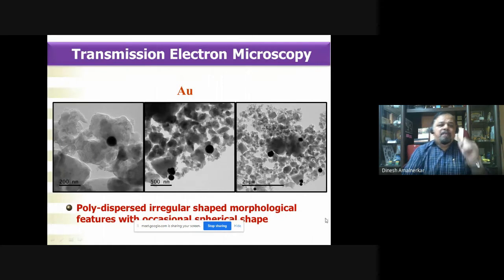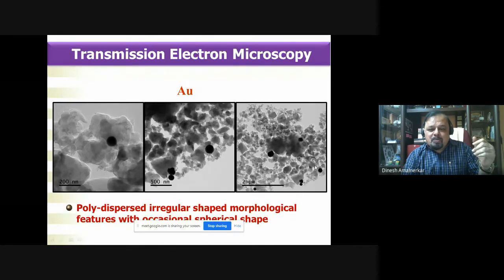Now, since we are not happy with the FESEM results, or so-called SEM results, we switched over to transmission electron microscopy to acquire a better understanding of what is happening within our material. Look at this low magnification, medium magnification, and high magnification. My student did this by himself and did not allow me to come inside, because only one person was allowed. So we could see here a good contrast image in TEM. You can see this is the nanoscale gold. You can see the faceted growth, and the spherical particles may be entrapped in an amorphous inorganic matrix.